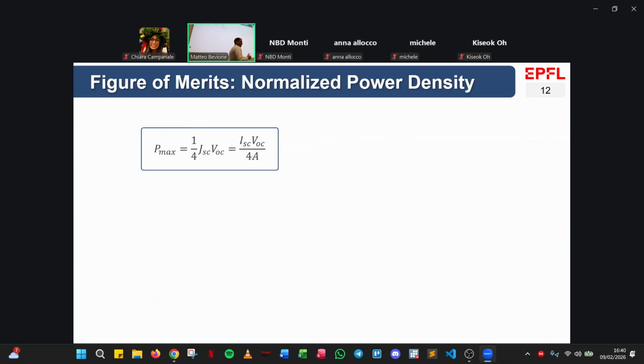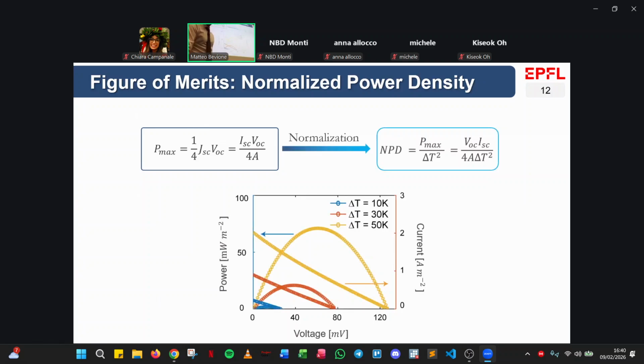So besides the thermopower, there is also this other parameter, which is the normalized power density, which gives you an idea of how much power you can produce given a certain temperature gradient. It's basically defined as the short circuit current multiplied by the open circuit voltage. If we represent that in this graph, the power-voltage relationship or current and voltage, we will see that the power-voltage curve has this nice shape. And that's what gives you the 1/4 that's there. You need half of the voltage to have the maximum and half of the current. And if we divide by the temperature gradient squared, we will get this MPD, the normalized power density, which is the second figure of merit we need. So just keep that in mind.